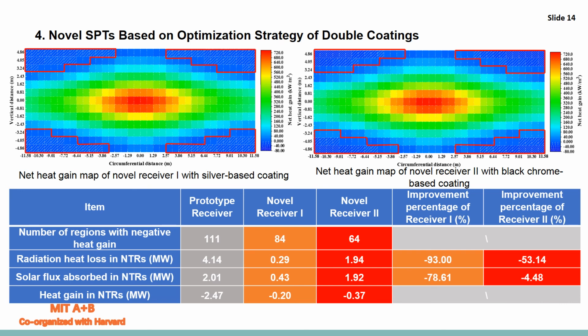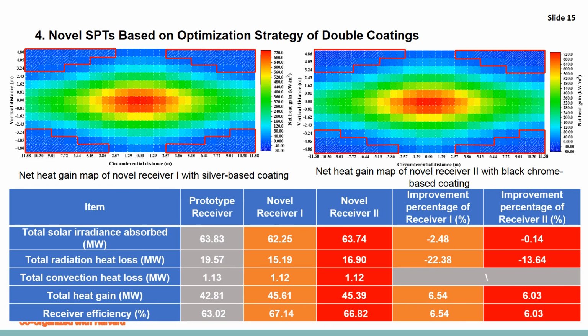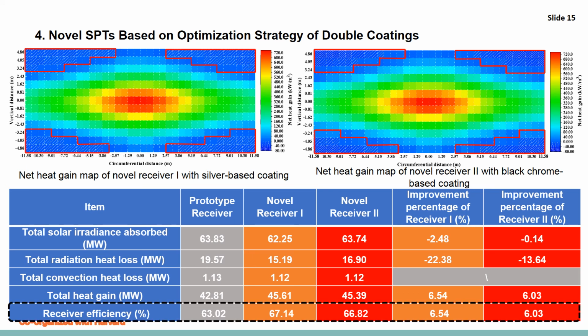But due to the reduced solar absorbance, the amount of solar absorption by NTRs decreased by around 78 and 4.5%. But overall, the net heat gain in the NTRs for the novel receivers 1 and 2 is effectively enhanced to minus 0.2 and minus 0.4 million watts from the original minus 2.5. As a result, the receiver efficiency of novel receivers 1 and 2 is effectively enhanced by around 6.5 and 6%, demonstrating that the coating optimization method plays an effective role in enhancing the thermal efficiency of the tower.